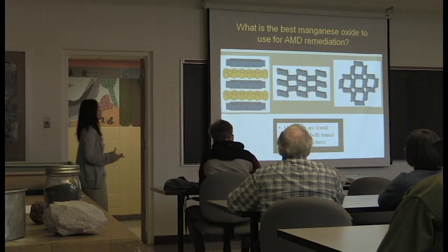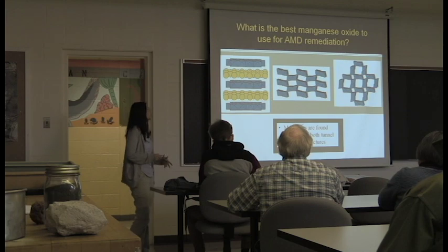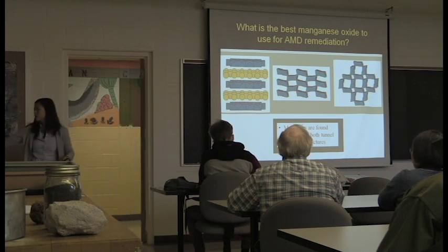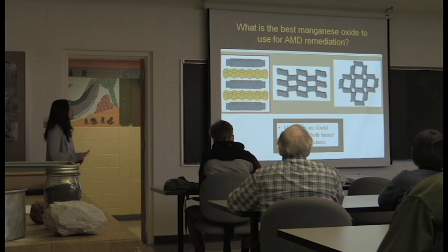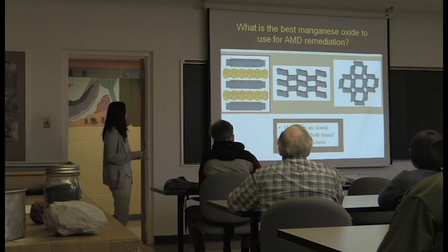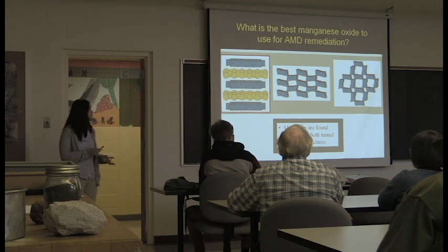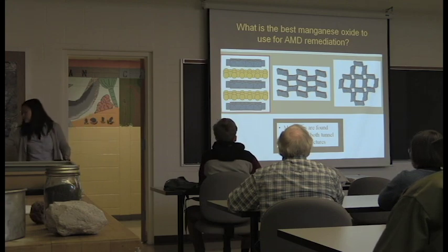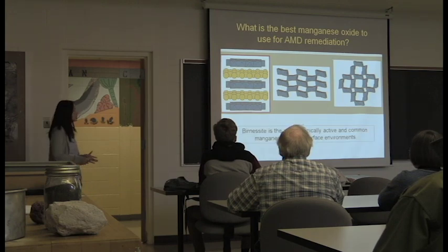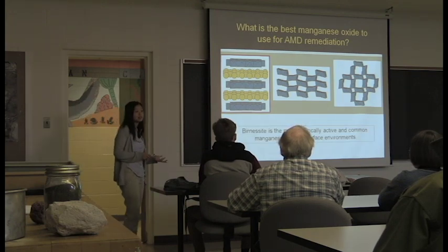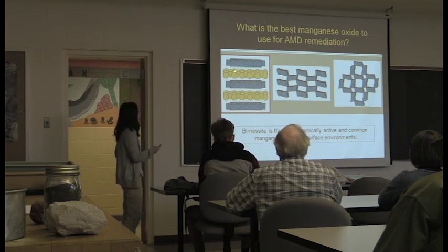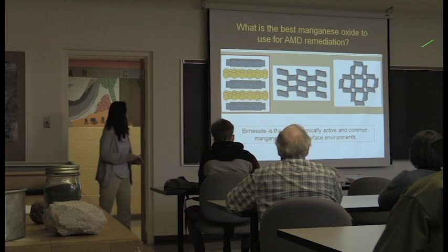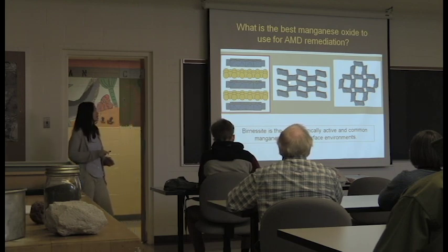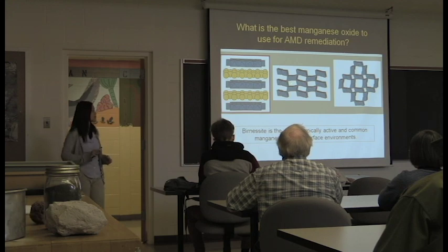But we have all these different manganese oxide minerals. We have layered structures, we have tunnel structures. Which one is the best for acid mine drainage remediation? Our hypothesis is that this layer structure, which is called birnessite, is the best, because this layer structure is not only the most common, it's also the most chemically active. That's because when you have these layers, you can interact not only on the surface, but also in the interlayer of your mineral, as opposed to your tunnels where it might be difficult to interact within the tunnel itself.